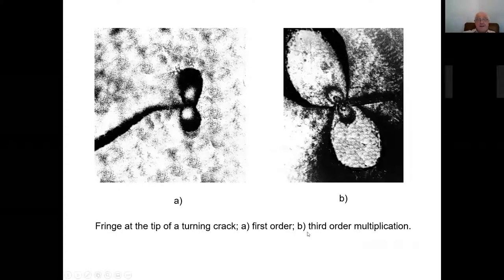So you have the case which we have also noticed for interface cracks, when you suppose that you have some symmetry, but the symmetry is not perfect, and then, of course, one of these cracks will take over the propagation, the other will remain. And here you have a fringe pattern for first-order multiplication and third-order multiplication in such a slice, which is growing. This is once again around 1 millimeter. You cut the slice normal to the crack front, which thickness may be around 1 millimeter, but it's not always the same, of course.